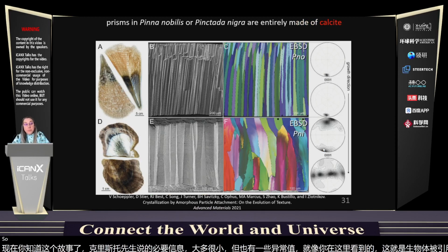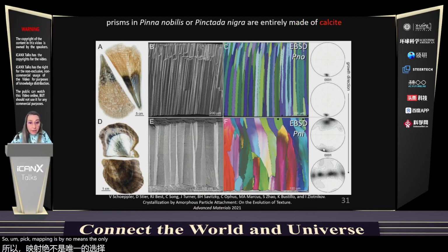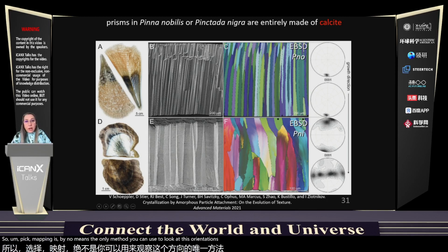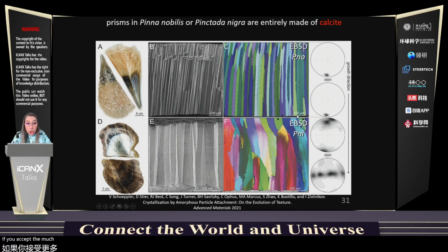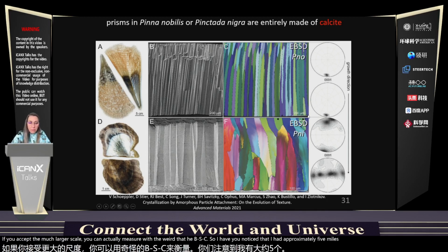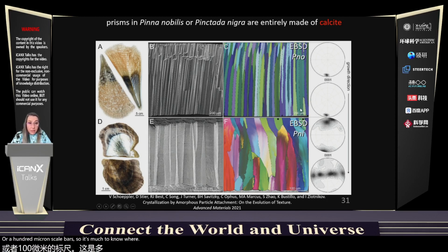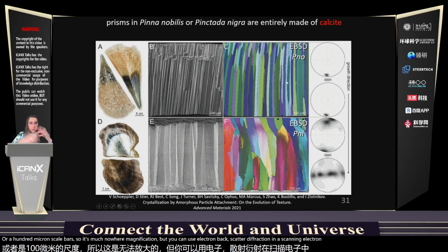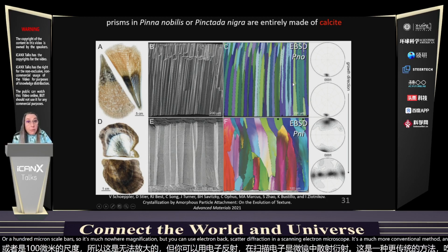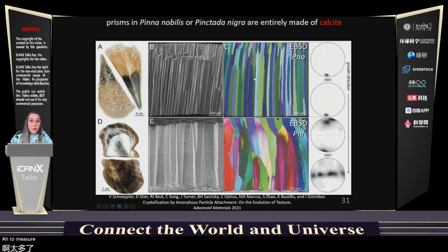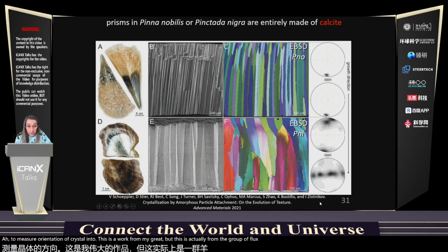So PIC mapping is by no means the only method you can use to look at these orientations. If you accept a much larger scale, you can actually measure it with EBSD. So have you noticed that I had approximately 5 micron scale bars? Here we have 200 micron or 100 micron scale bars. So it's much lower magnification, but you can use electron backscatter diffraction in a scanning electron microscope. It's a much more conventional method, but extremely useful to measure orientation of crystals. And this isn't work from my group. This is actually from the group of Igor Zlotnikov at TU Dresden in Germany.